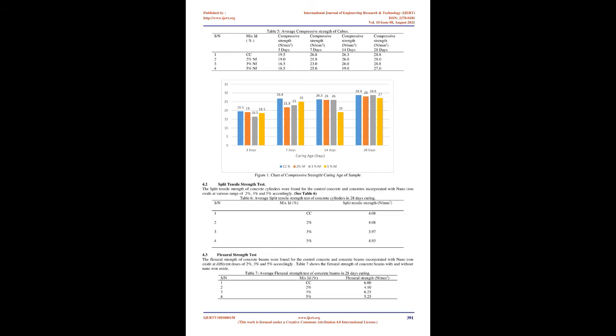Laboratory Procedures: Mixing Processes and Production of Test Cubes - Manual mixing method was adopted in preparing the concrete for placement. First the sand was measured, followed by the measurement of OPC and nano iron oxide which were thoroughly mixed until uniform color was obtained, followed with the measurement of crushed granite until its mixes are uniform. Water was next measured in order to achieve the required water to cement ratio of 0.55. The process is in accordance with BS 1881, Part 125, 1986. Absolute volume method was adopted for measurements of the volume of materials used in mixing the concrete (Neville and Brooks, 2002).